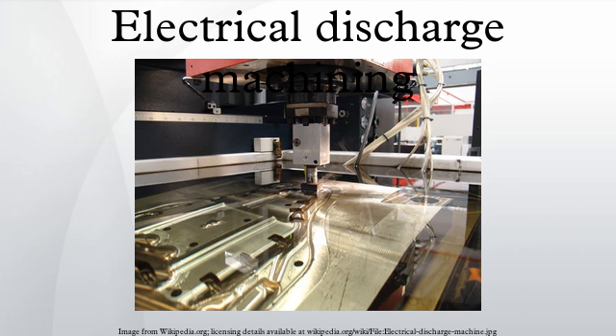Wire EDM. In wire electrical discharge machining, also known as wire cut EDM and wire cutting, a thin single-strand metal wire, usually brass, is fed through the workpiece, submerged in a tank of dielectric fluid, typically deionized water. Wire cut EDM is typically used to cut plates as thick as 300 mm and to make punches, tools, and dies from hard metals that are difficult to machine with other methods. The wire, which is constantly fed from a spool, is held between upper and lower diamond guides. The guides, usually CNC controlled, move in the X-Y plane.